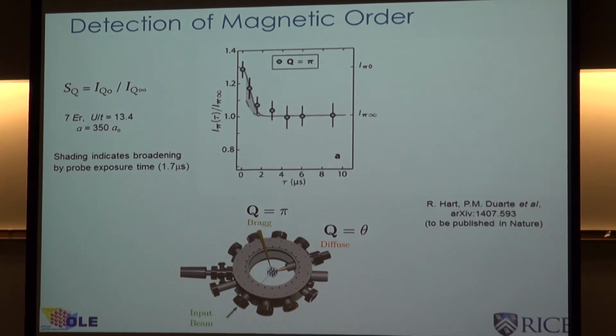All right, so this is what we see. So again, this is the spin structure factor. These are the parameters of the lattice. And this is a function of release time from the lattice. We see a peak of 1.3, and after 3 or 4 microseconds, that quickly decays into 1. And there's no adjustable parameters in this theory. This is just a simple fit based on the Debye-Waller factor.